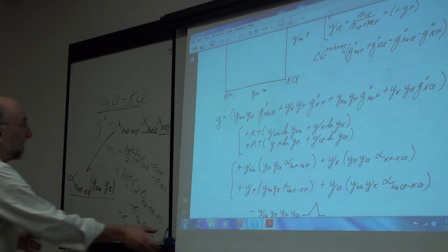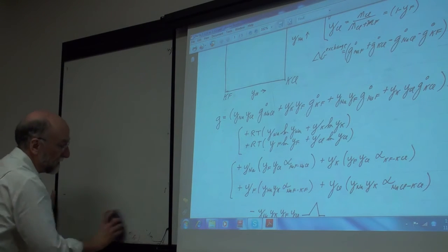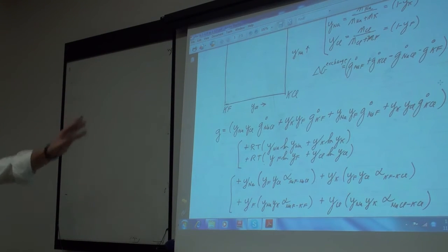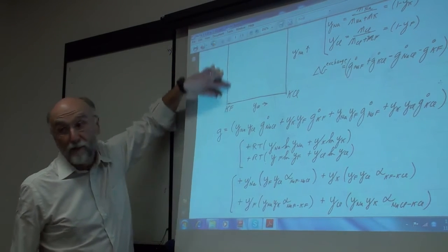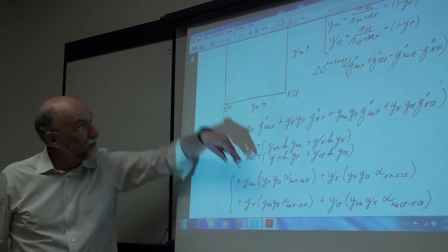And now just to continue to prove a point, let's take this equation. I've still dropped the last term here. But this is the sublattice model, two sublattices, Bragg-Williams mixing. By the way, these alphas, of course, can vary with composition. This alpha will vary with composition along here. It doesn't have to be constant, it can vary with composition.